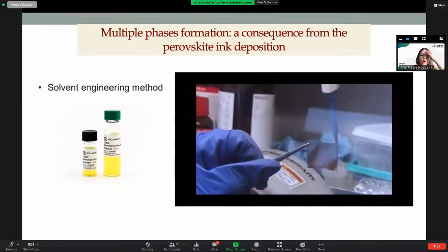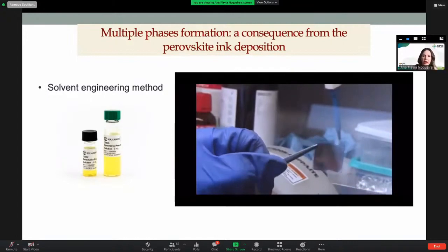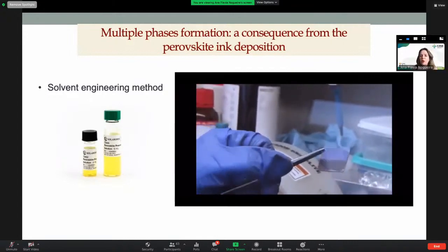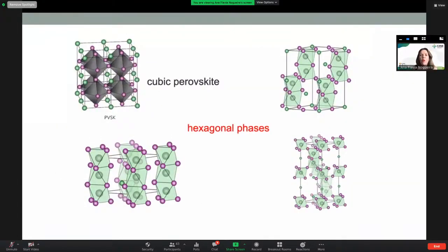Because of all of these low-grade chemicals, and because you are doing it manually, at the end of the spin coating we end up not only with the perovskite in a cubic form, the one that is ideal for solar cells, but also with what we call the hexagonal phases. We have 2H, 4H, 6H, three different types of hexagonal phases. They're really hard to control because these hexagonal phases are actually thermodynamically more stable than the cubic one.